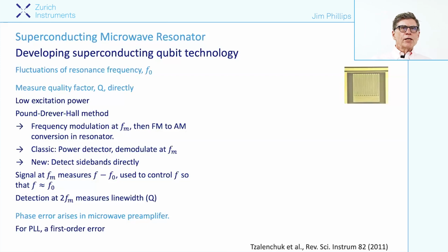An example is superconducting microwave resonators used for quantum computing devices, where often one just studies the microwave resonator in order to optimize one's material process. What happens here is that noise in the resonator is very important to get to a minimum level, and the two-level systems that create the noise shift the resonator frequency and, of course, broaden its line width.